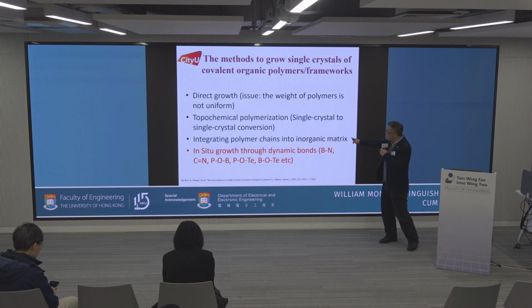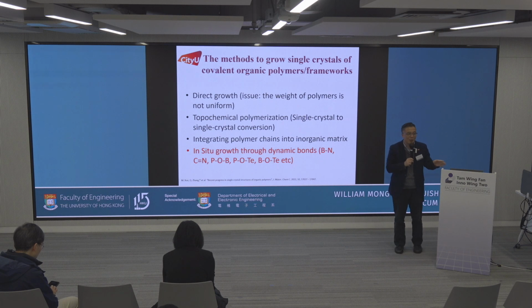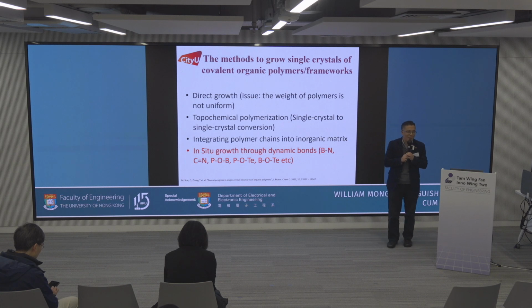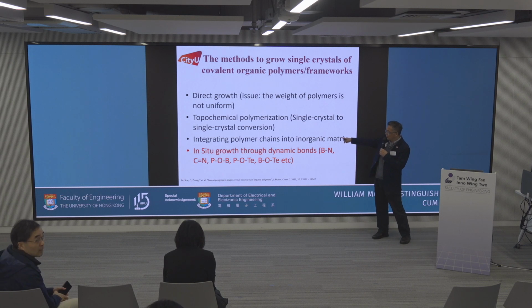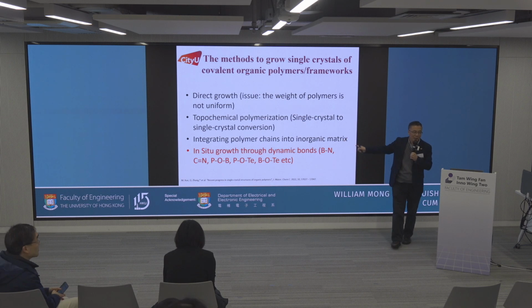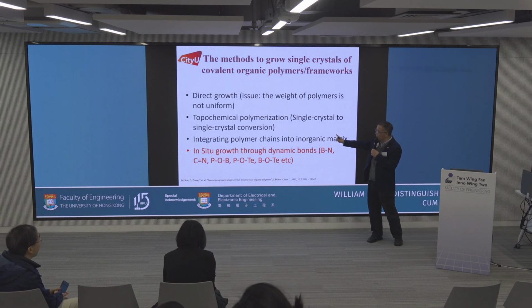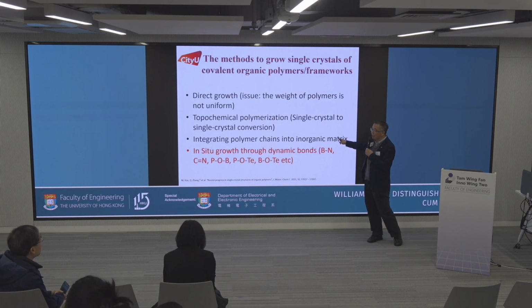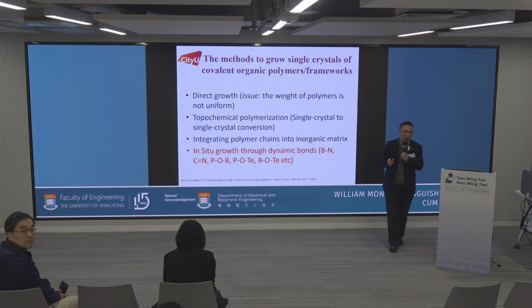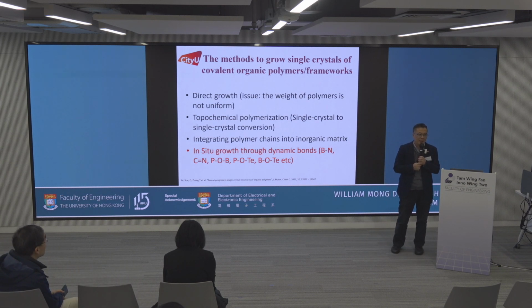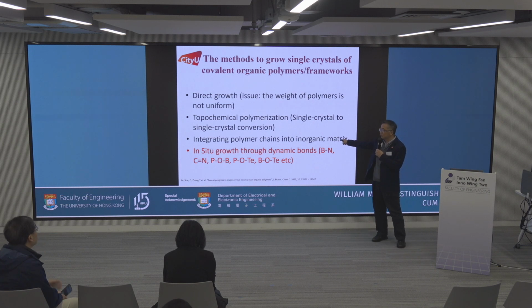And then the third method is to put the polymer chain into an inorganic matrix. In this case, we know that an inorganic matrix can easily grow single crystals. In his earlier work, Professor Mercouri did a lot of research trying to put the conjugated polymer chain in the inorganic matrix. But at that time, I believe Professor Mercouri didn't get any single crystal of the composite. So in my group, when I was at NTU, we developed a method to integrate polymer into the inorganic matrix, grow the single crystal, solve the crystal structure, and then solve the polymer chain. I think this was the first time it was reported in the literature.